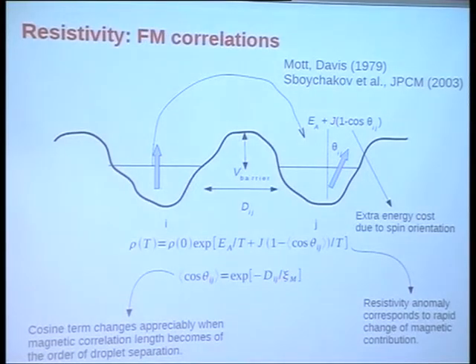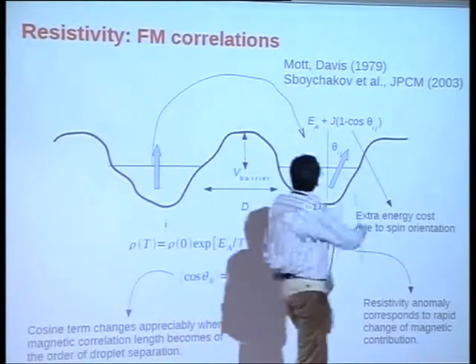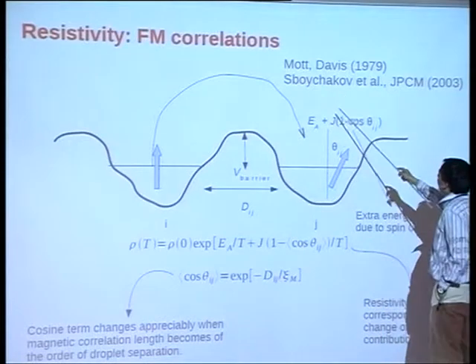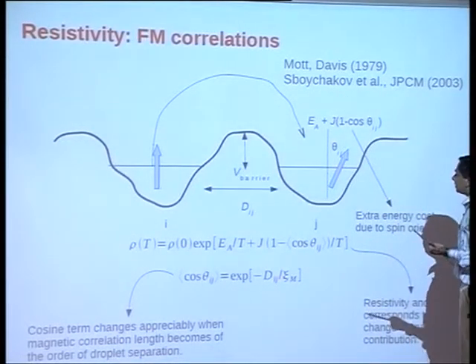One can then go and estimate the puddle sizes, and one finds that the samples are relatively close to the percolation metal insulator transition. In fact, one of the samples is metallic, the rest are insulating but very close to the metal insulator transition. We don't guarantee this because it's a very crude estimate, so except for the most metallic and most insulating, we remain a bit ambivalent. Nevertheless, it's fairly close. Then following Mott and Davis and Sboychakov, etc., in 2003, we